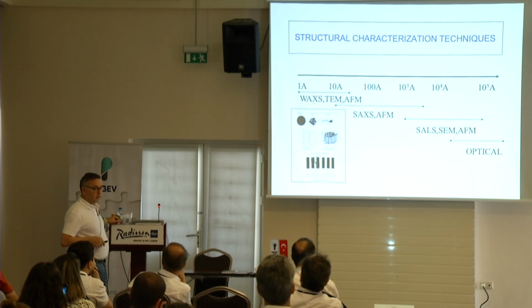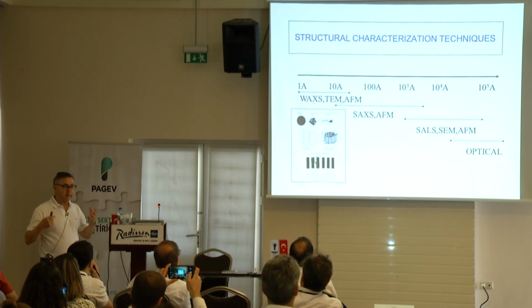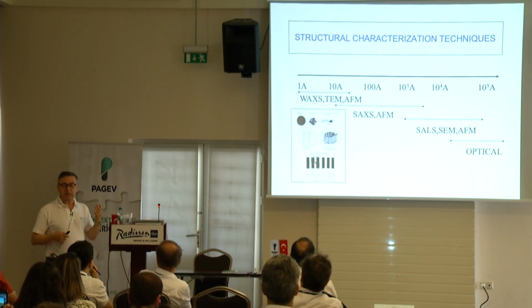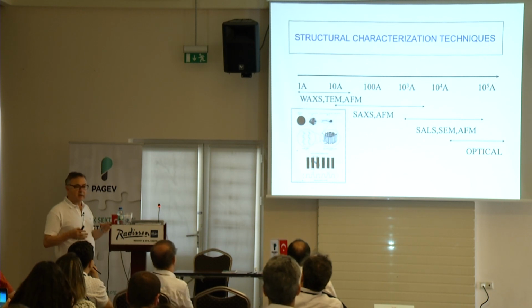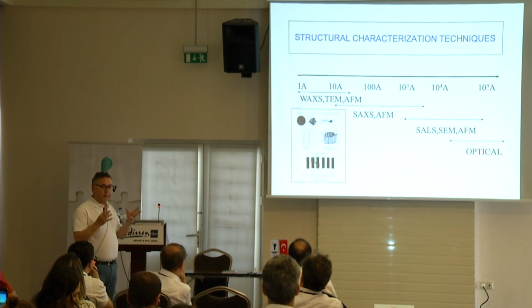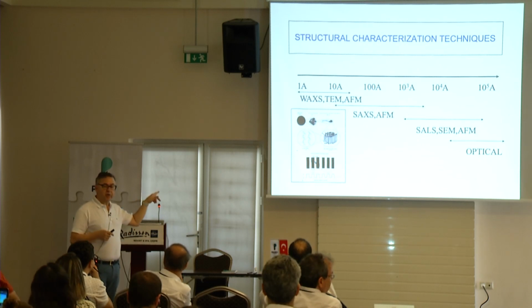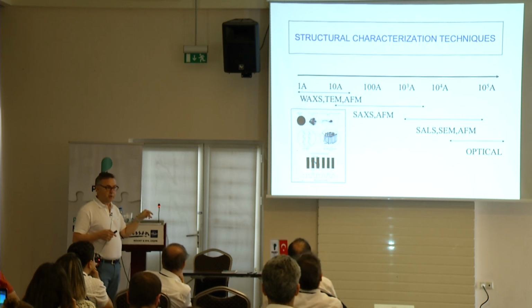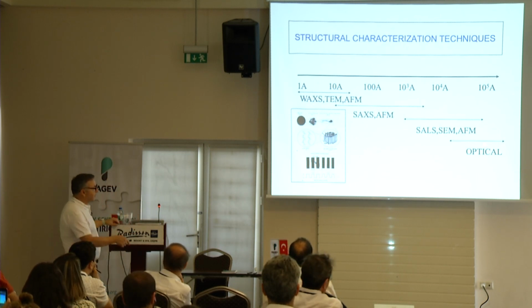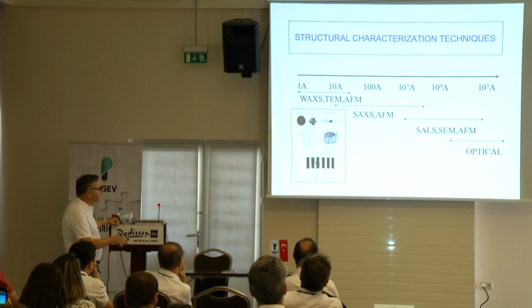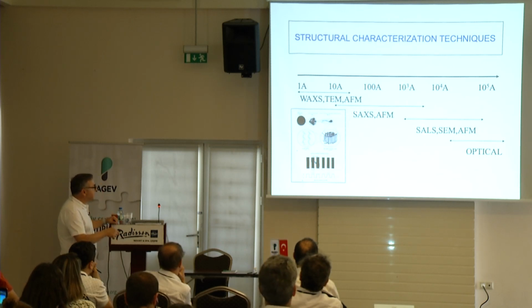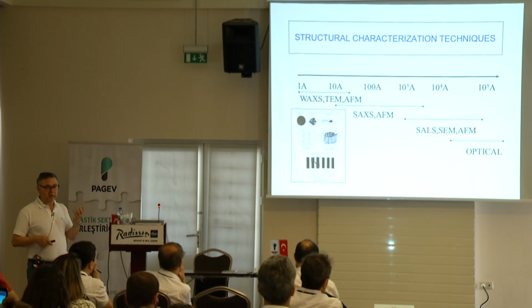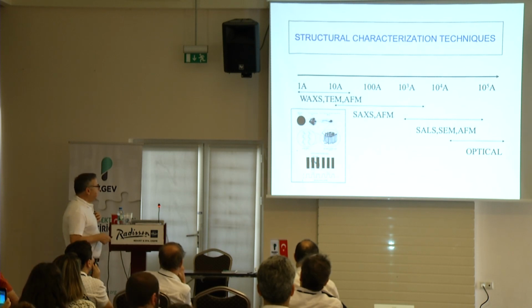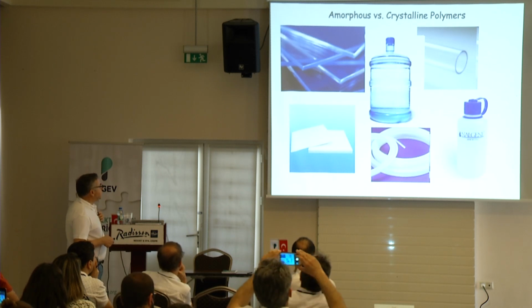Every laboratory must have a microtome and an optical microscope at the minimum, just so that you can slice it, especially if you have problems with making molded parts, and there are issues related to warpage, shrinkage, and so on. Some of this directly points to the morphology that you have created by the process. So you must have at least this one, even if you don't have AFM or TEM and X-rays. If you have an AFM and SEM, that's even better. And going down to the X-ray gives you much more information. I'm going to give you examples of what kind of information you can get from these techniques. Okay? So you are in the business of making all kinds of plastics.